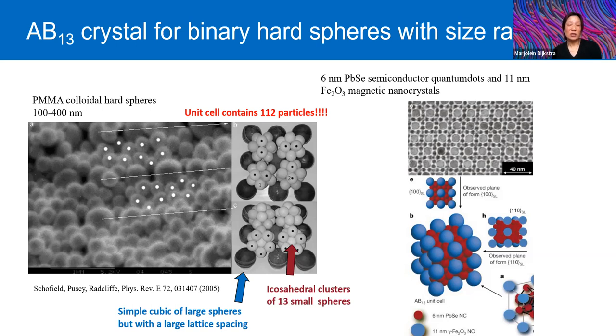And the crystal that always intrigued me was the AB13 cluster phase, because it is stable in a binary hard sphere mixture, so just small balls and big balls mixed together. And if you are at the right conditions, it spontaneously forms this very exotic AB13 crystal phase. And this crystal phase consists of a simple cubic of large spheres. This is already a very unusual lattice for hard spheres, because usually they form hexagonal lattices.